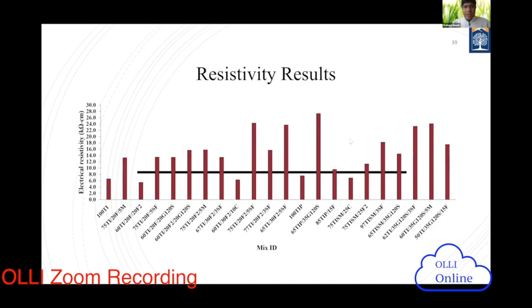So these are some results. Again, these are the mixtures that we have used. The first one is the original mixture, 100% Type I Portland cement. Then, just to compare, one of the better quality mixtures: 65% cement, 35% slag, G120S. How big are the resistivity values? Just on 28 days, 28 kilo-ohm centimeter. So that gives an idea.